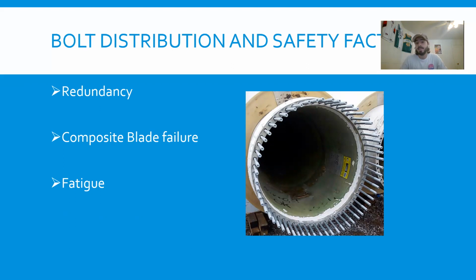Also, I could not find a definitive number for how many bolts for this sized root radius. However, what I was finding is that generally these bolts seem to be spaced out around 5 degrees all the way around the circumference of the root, and you see numbers typically 64 to 72 for these 3 megawatt applications.